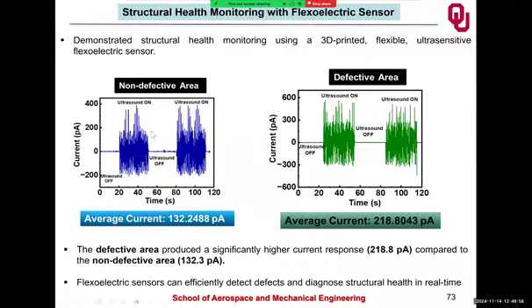It is very interesting to see that from the non-defective area, the average current response is 132, whereas from the defective area, the current response is higher. So it means that we can distinguish the sensor response from different locations, based on the defective area versus the non-defective area. So these flexoelectric sensors can efficiently detect defects and can be used for structural health monitoring applications.